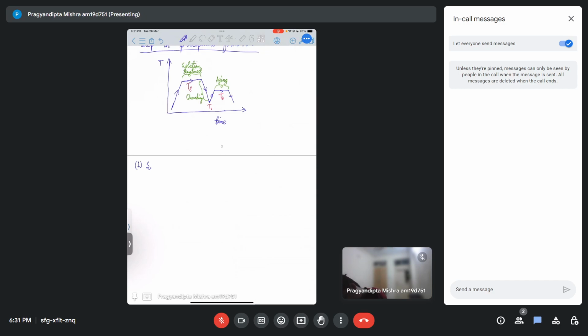First step, solution treatment. What you will do is heat the alloy. Because you are heating the alloy, you have increased the temperature, so now you can dissolve more of the secondary phase particle, the secondary element. You will see a single phase region. This will dissolve any precipitate or phase that might be present.